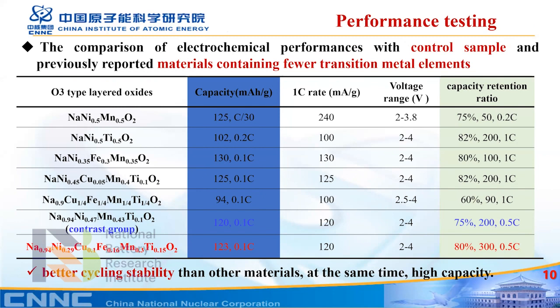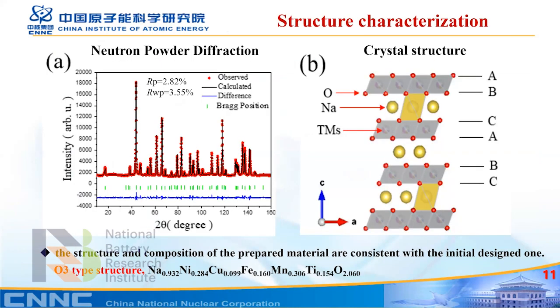The results are shown in the table. You can see that our designed five-component material shows better cycling stability than some reported good positive electrode materials, and also relatively high capacity. Here, I will not introduce more about this. We have this measurement capability, but I will not go into detail, but I will show some neutron-related skills. Here is neutron powder diffraction technology. We closely collaborate with spallation sources and reactor sources, and we also collaborate with our AONSA colleagues. This picture comes from Australia, the OPAL reactor, and it shows very good resolution.